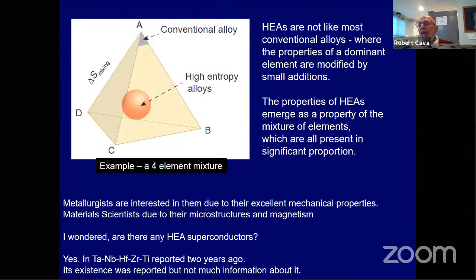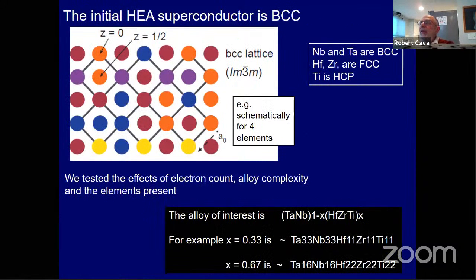So again, I was sitting at a conference and I saw some metallurgist give a talk on this, and I said, well, I wonder if there are any high entropy alloy superconductors. Well, yes, there is one: tantalum, niobium, hafnium, zirconium, titanium. Niobium and tantalum are BCC, hafnium and zirconium are FCC, titanium is HCP. These are normal kinds of crystal structures for metals. When you mix them together in roughly equal proportions, you get something that is body-centered cubic, BCC.